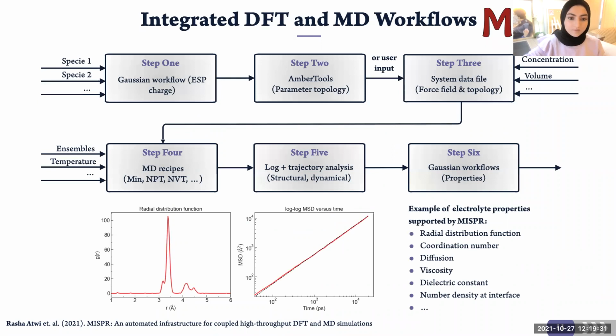The molecular dynamics workflows build upon the results of the density functional theory workflow in terms of taking the optimized geometries from the DFT calculations and extracting the electrostatic partial charges, which are used in order to generate force field parameters that are needed to model the interactions in the solution. The workflow allows us to do calculations in different ensembles like minimization, NPT, using default MD recipes or defining the user's own MD recipes or sequence of steps, and then finally performing the analysis on the output and trajectory files from the MD simulations to derive various thermodynamic, structural, and dynamical properties.